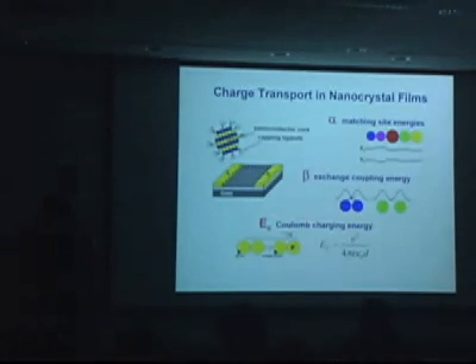The problem is that, for example, if you have a granular system, it's just energetically costly to put a charge on a conducting sphere, to localize charge. And this will lead to an electrostatic charging energy that is inversely proportional to the size of the particle. So when particle size goes down, charging energy goes up, and you open what is called a Hubbard gap. And so the material that appears to be a good conductor can in reality end up being a Mott insulator. And there are Anderson localization and a whole bunch of other problems.